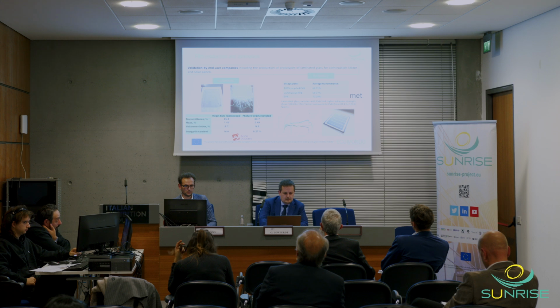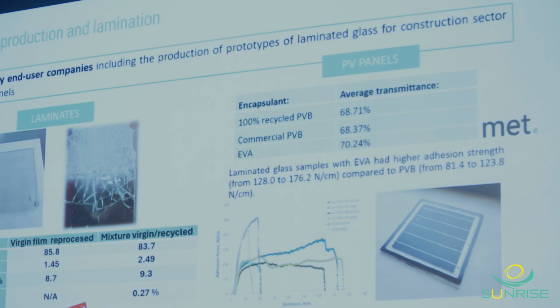So what we have done in the project, we have been working with these mixtures of virgin and recycled PVB, and we have compared. In this comparison, this is compared with a virgin film, but this virgin film has been reprocessed. Because if we compare with virgin film as it is, just processed once as a product, these values of haze are lower, of course, and these values of transmittance are higher.